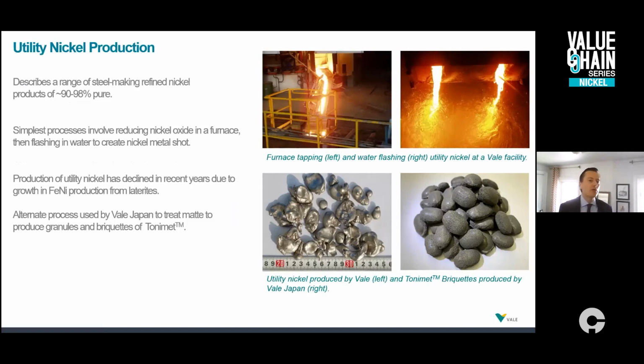Getting into the refining processes used to create less pure forms of nickel, we can talk about utility nickel production. One's very common, now less so. Utility nickel describes a range of steelmaking nickel products that vary in purity from, say, 90 to roughly 98%. The simplest processes involve reducing nickel oxide feed material in a molten state and then flashing that material in water to produce a utility nickel shot. And you can see photos of that happening at a Vale facility in China on this slide, as well as a photo of nickel shot.